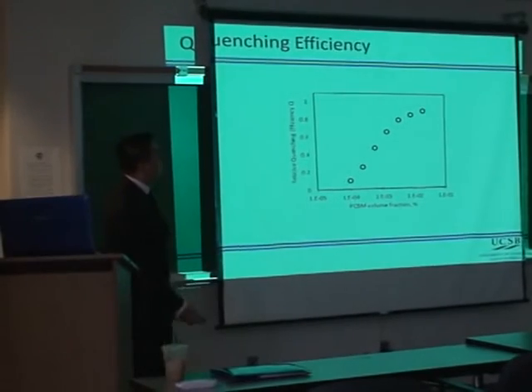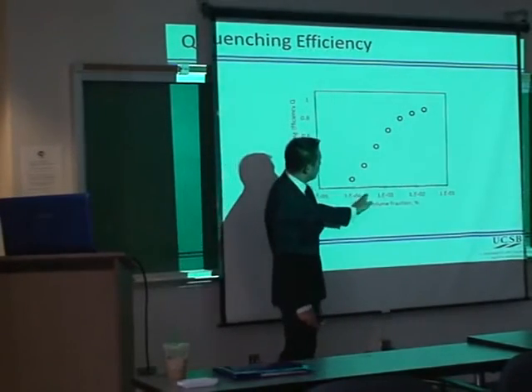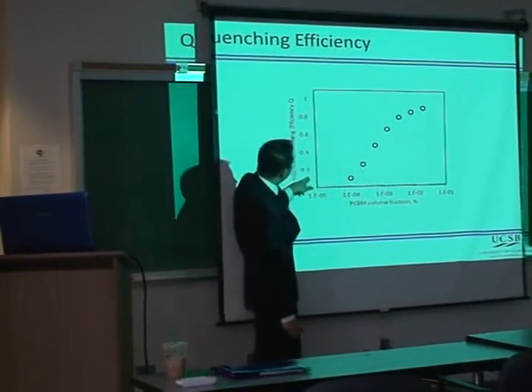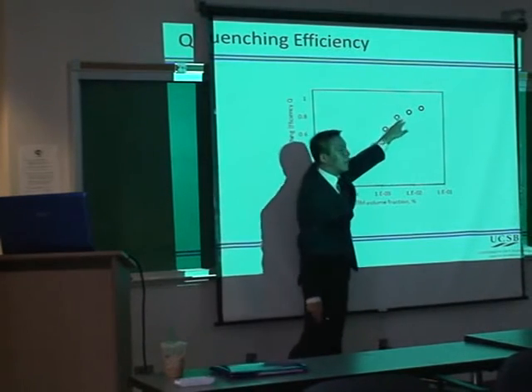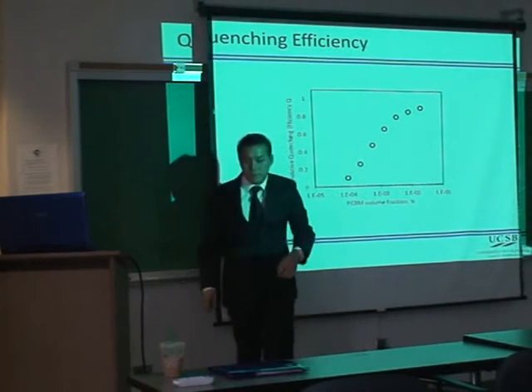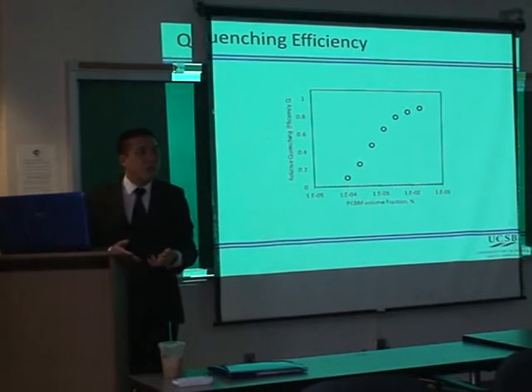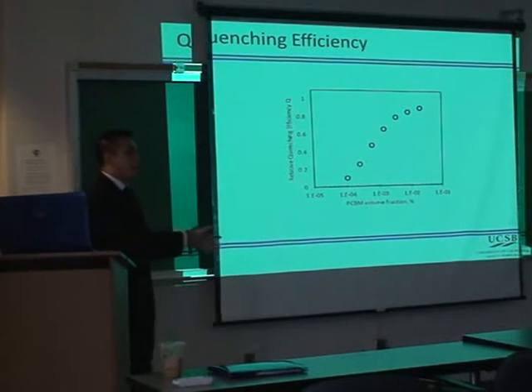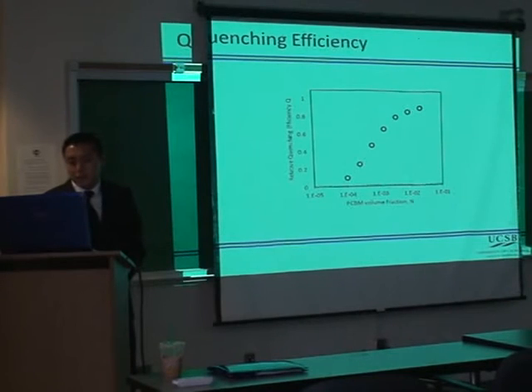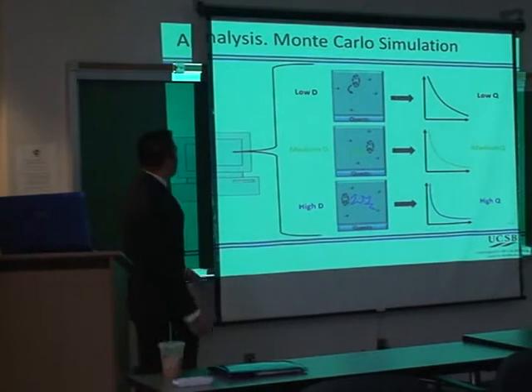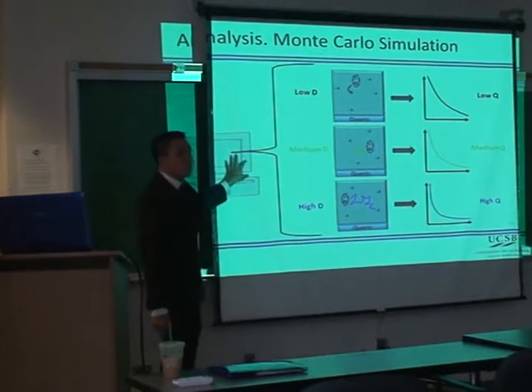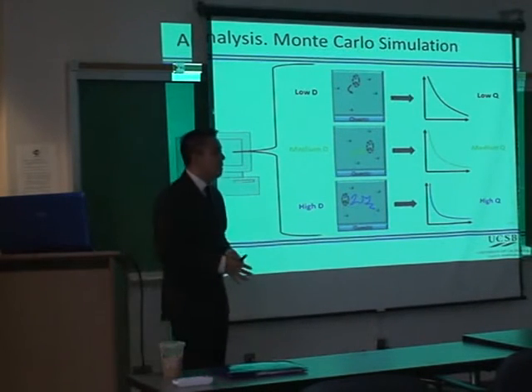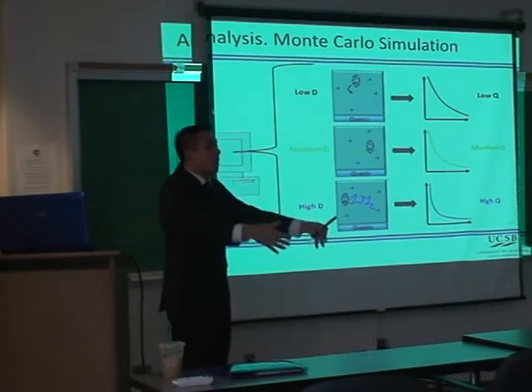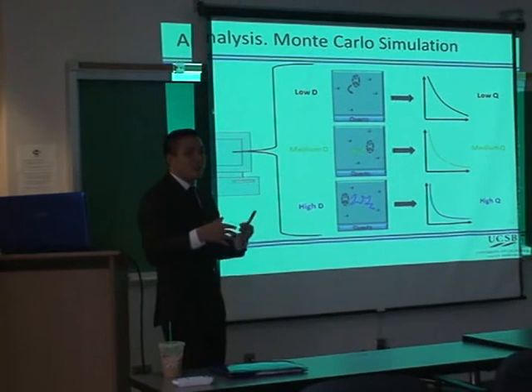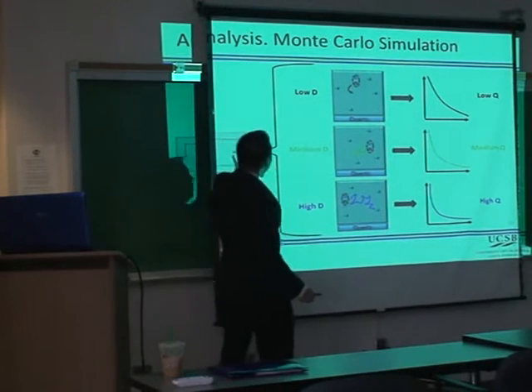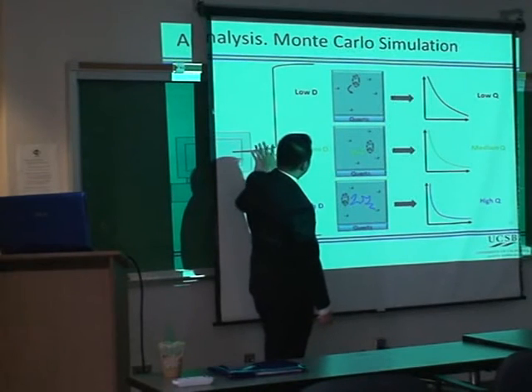So we could do this for a number of different films. We could prepare films with different concentrations of PCBMs, and each of those we could calculate a quenching efficiency. And this is the kind of plot that you would get by doing that. So the next question is, how do we connect this measurement with a model to determine the exciton diffusion length? So this kind of symbolizes the Monte Carlo simulation. And a Monte Carlo simulation is basically a program that runs multiple trials. It's kind of a random process. And that's how it basically determines and fits for the exciton diffusion length.